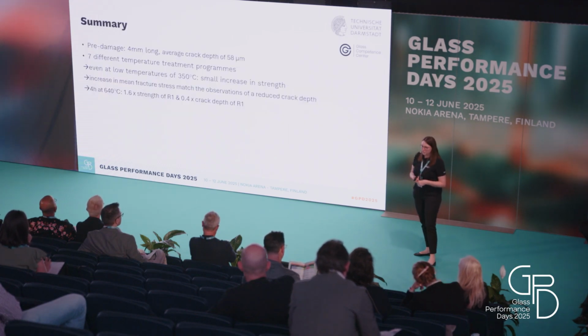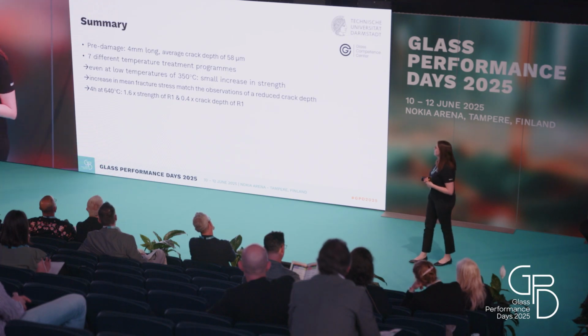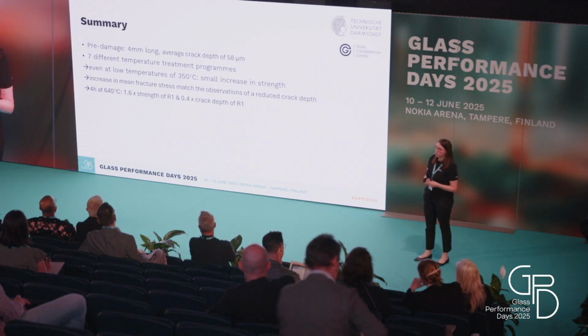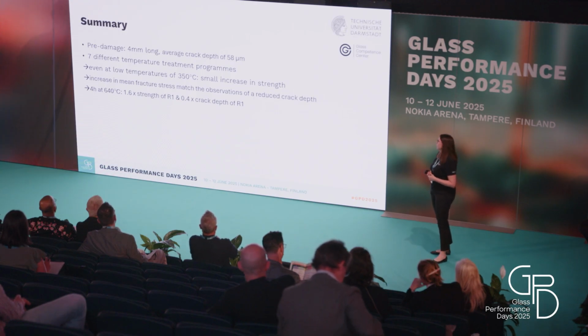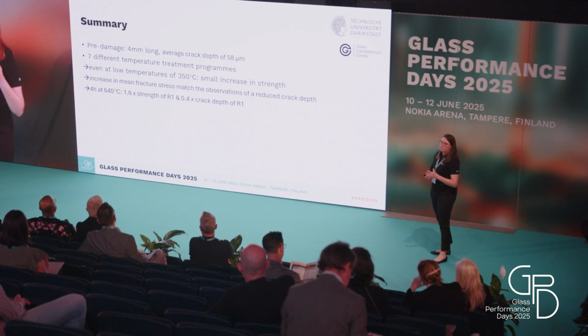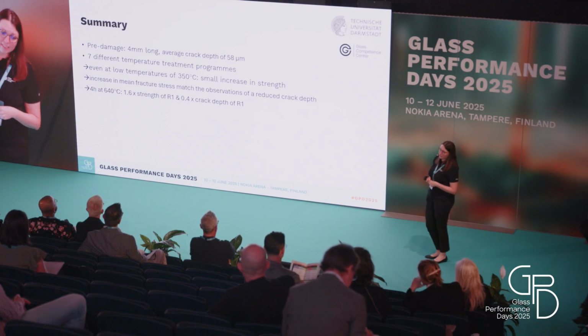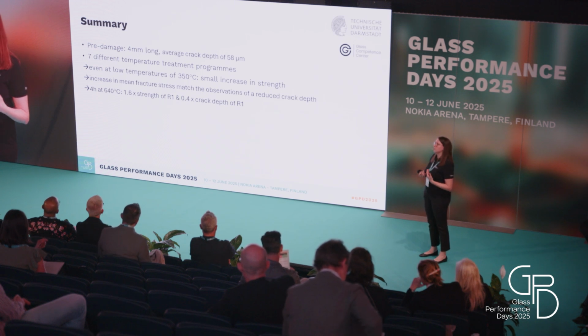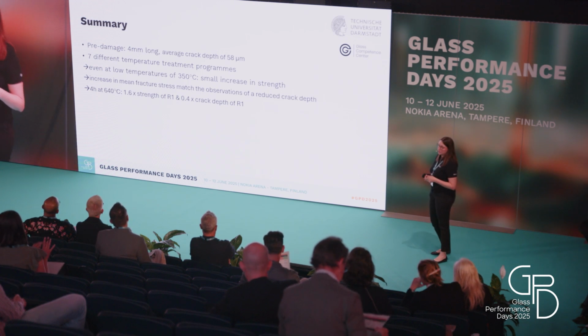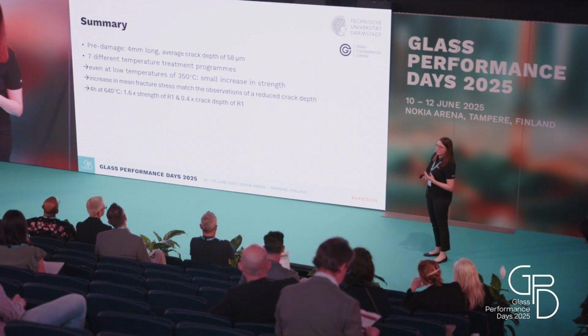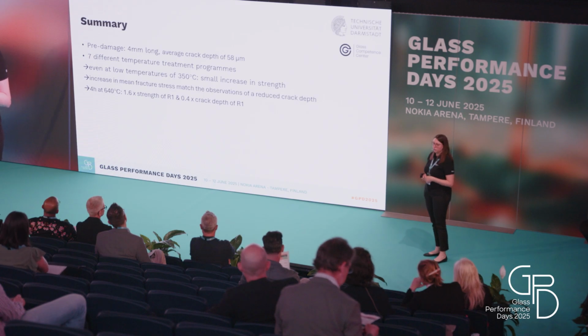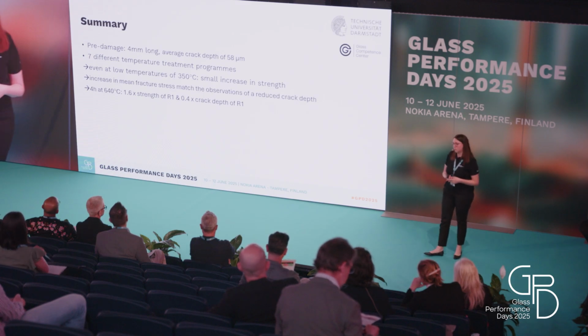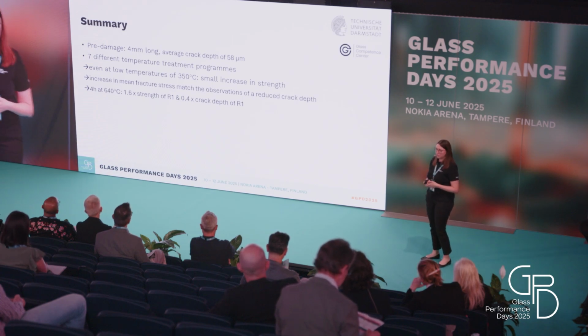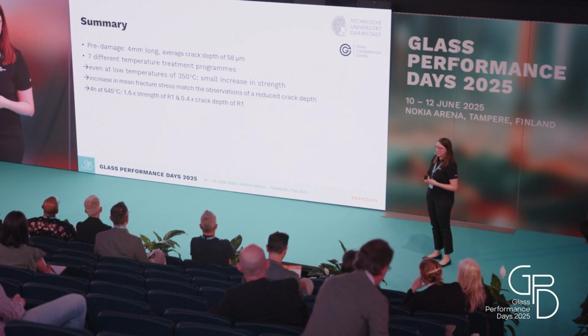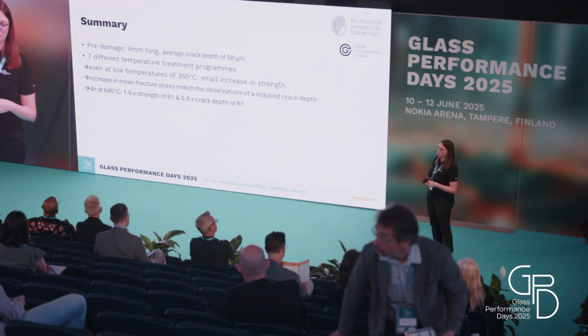So let's come to the summary. We pre-damaged a new soda lime silicate glass. The pre-damage was approximately 4 millimeter long, and the average crack depth was 58 micrometer. This crack depth was measured after the ring-on-ring test. We investigated 7 different temperature treatment programs, and for all of those programs, we could observe an increase in strength even at the low temperature. The increase in the mean fracture stress also matches the observation of a reduced crack depth, and we had the best results for a treatment of 4 hours at 640 degrees Celsius, where we achieved a 1.6 times strength compared to our reference series and a 0.4 times crack depth of our reference series.